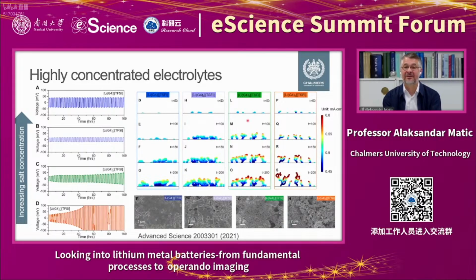And then comparing to phase field modeling results, you can see again here that there is a match, that at low concentration, you actually form this kind of whisker-like, dendrite-like structures, and that at high concentration, you obtain a much more dense deposition.